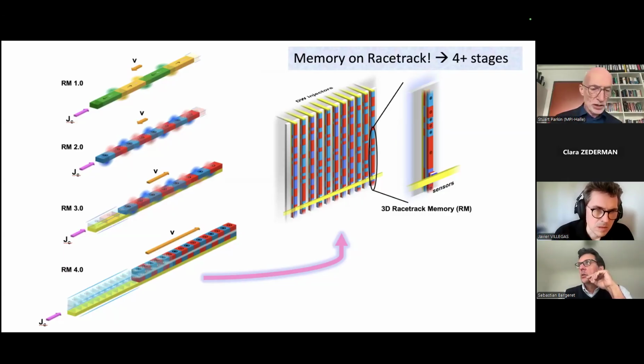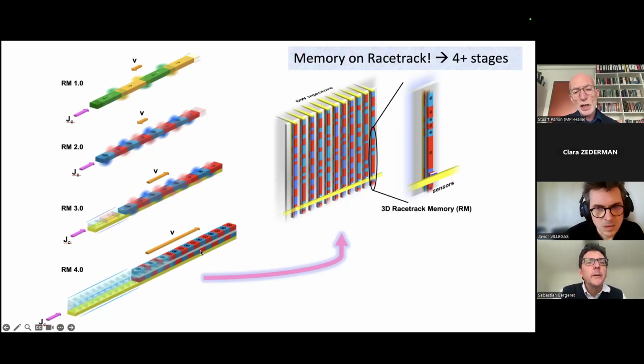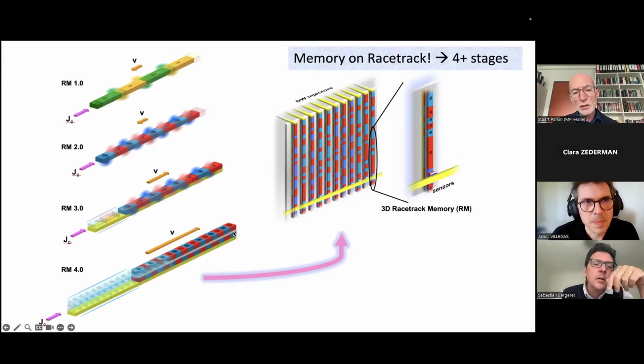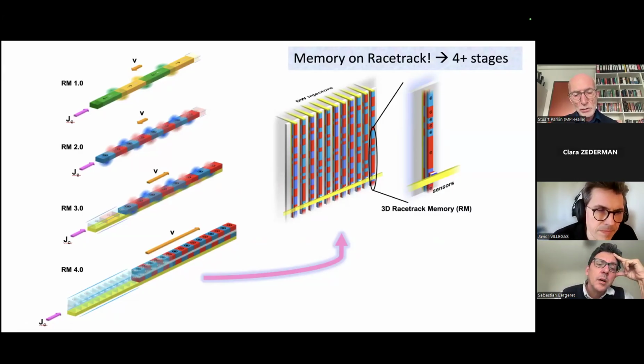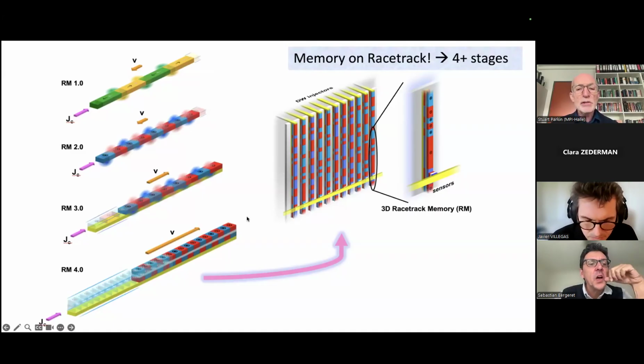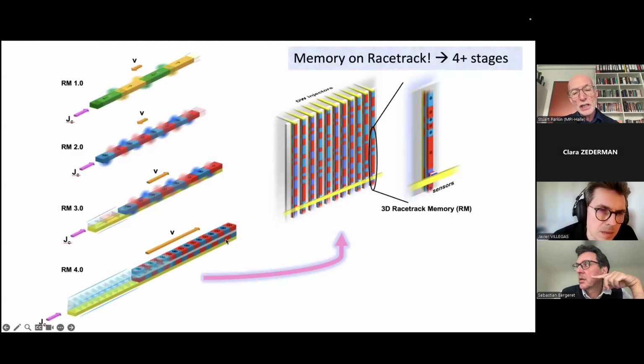And finally, the most interesting racetrack, 4.0, is where we showed in 2015, so all of this some time ago, we built what we called a synthetic antiferromagnet. In this case, I think you can see from this cartoon that you have a lower racetrack coupled through a very thin layer, which is typically ruthenium, a few angstroms thick, which couples the lower magnetization in the racetrack to the upper racetrack layer anti-ferromagnetically, so that the lower racetrack is essentially a mirror image of the upper racetrack, so that at any position along the racetrack, the upper and lower magnetic moments coupled anti-ferromagnetically have the opposite magnetization. So you can eliminate the moments so that there's no net magnetization.